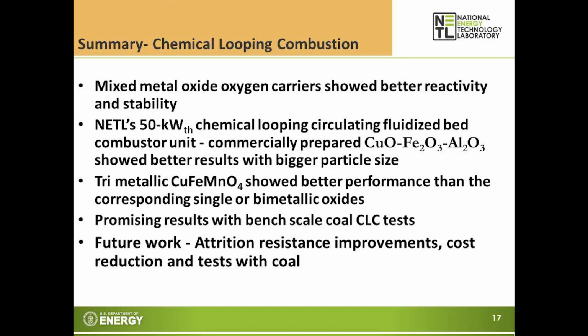So, a summary of the chemical looping combustion: mixed metal oxide oxygen carriers showed better reactivity and stability, and the commercially prepared copper, iron, aluminum oxygen carrier showed very promising results during the test in our 50 kilowatt thermal pilot scale unit. And we saw better results with the bigger particles. The trimetallic copper, iron, and manganese also showed better performance than the corresponding single and bimetallic oxides. We saw promising results with bench scale coal chemical looping combustion with the copper, iron, aluminum oxygen carrier. For future work, we would like to improve the attrition resistance, lower the cost, and do more tests with coal.